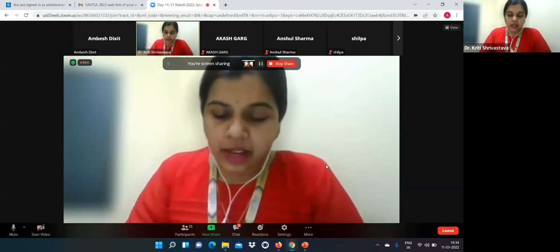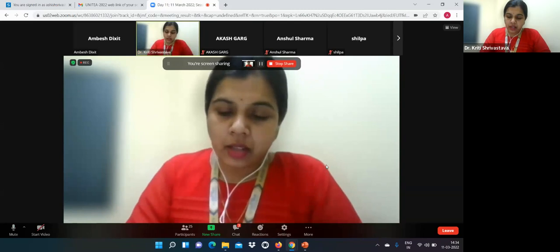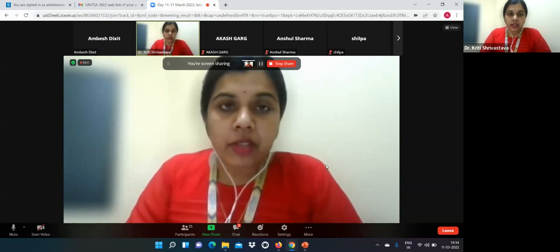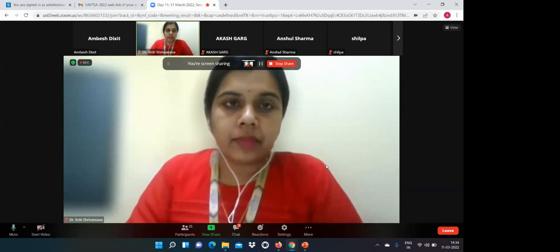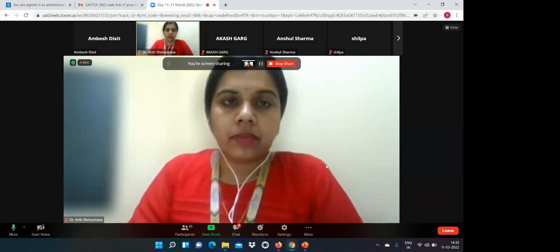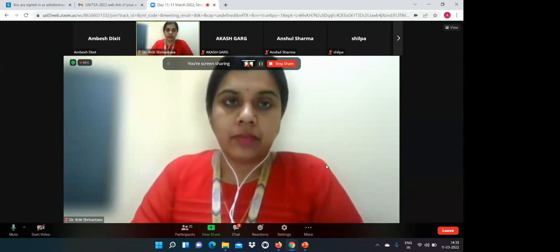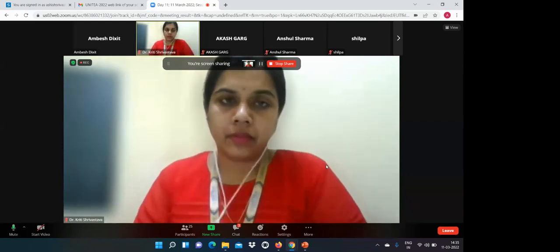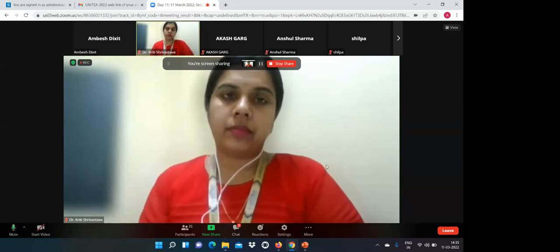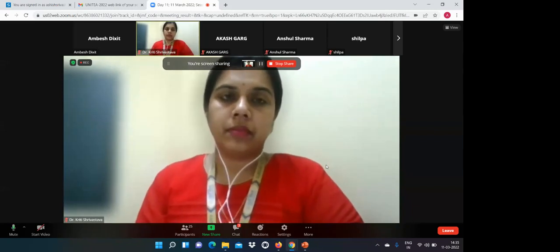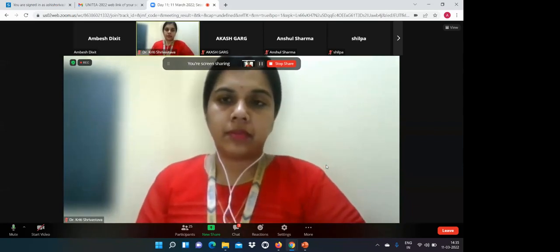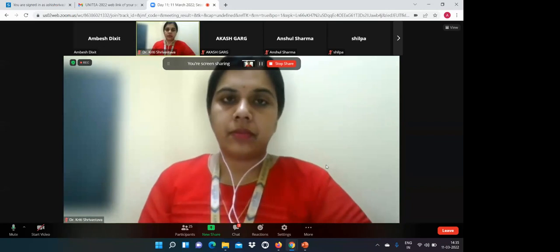Thank you, sir. The next question is, what are the factors that affect the performance of DSSC? Very simple question and very interesting question. Simple in the sense that everyone should think of stability. So the first thing is dye molecule stability. Dye molecules get degraded at higher temperature, so temperature is a big factor. Moisture is a big factor too, because dyes are organic molecules, they can bind with moisture and make a new molecule. That molecule may not have any absorption capacity at all.